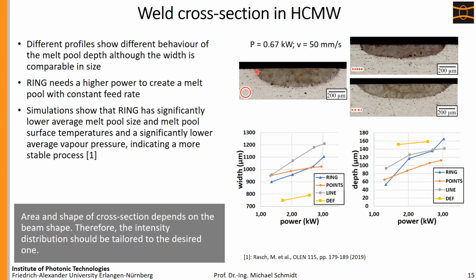If you look at the welding cross sections, you can see here what happens with the ring shape. You can see here the line, and the dotted line, and these images show you the width over the power and the depth over the power. The ring needs a higher power to even create a melt pool with a constant feed rate. Nevertheless, as it has a lower average molten pool size and molten pool surface temperature, it indicates a more stable process. So the most stable process is always with the ring shape, as you might have expected, whereas the others behave differently but not as well as we wanted.